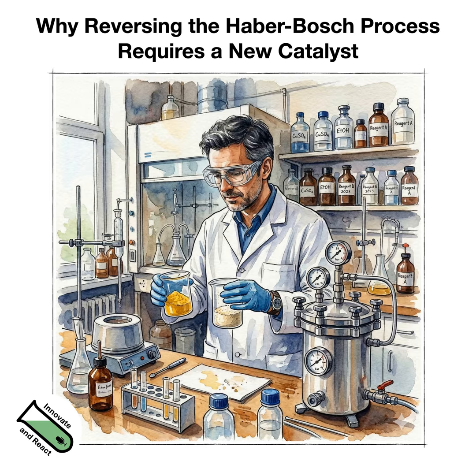So that simplified view seems to be true to some extent, and is also nothing that we invented. But it can be applied to the iron and cobalt case for ammonia decomposition with very nice results. And that was also what our theory colleagues could confirm. So you climb from the iron position towards the top of the volcano by alloying, or putting in just the right amount of cobalt, moderating the too strong binding to nitrogen, making it a little bit weaker, but not too weak. And how does this combined iron-cobalt catalyst then compare with the ruthenium?